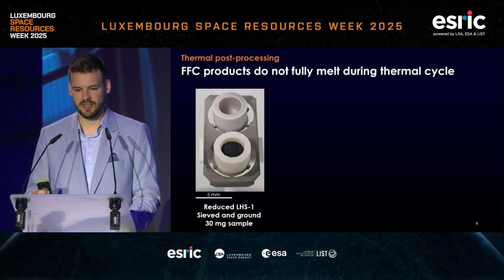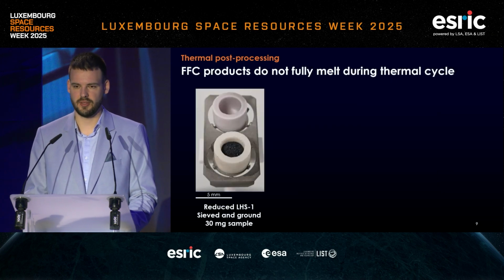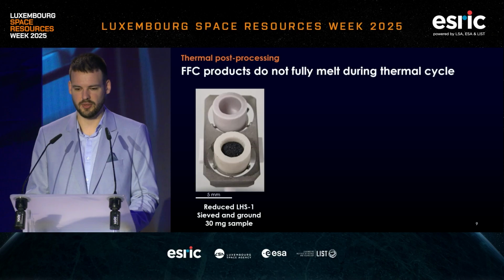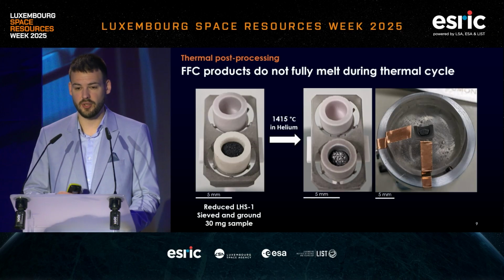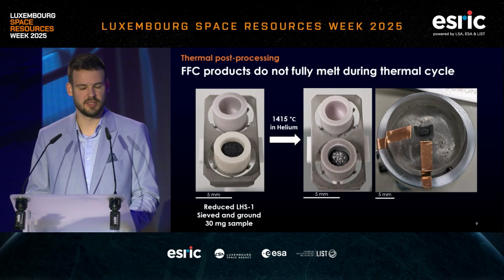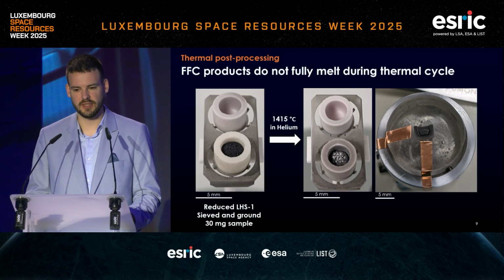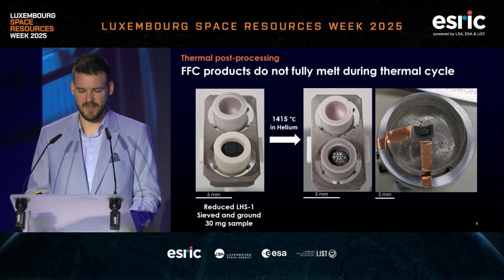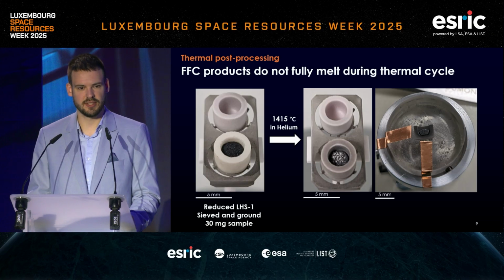So as I said, if we apply this to actual products that come out of the FFC process, here we took some reduced LHS1 and also applied different temperature profiles, but there we observed that even if you go all the way up to 1,415 degrees C, which is kind of the limit of our instrument, we do get consolidation, but what we can see is that we get more of a semi-molten, sintered ingot rather than nicely consolidated billet.